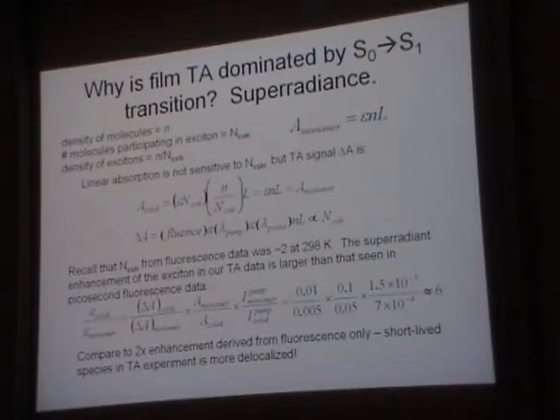Because we're doing these experiments on films with a peak OD of 0.1 or less. So my students said, oh yeah, this experiment is way easier than doing it on the solution Tetracene, and I was surprised. But the reason I was surprised is because I didn't believe the papers that I published, right, which is always a problem. The papers I published said that you have superradiance, right? You have this enhanced oscillator strength, and if you believe that, pump probe becomes a lot easier,